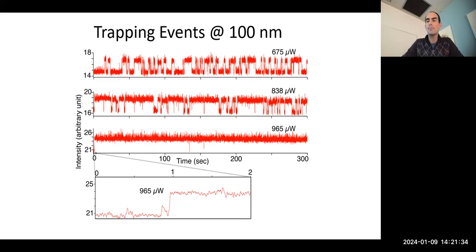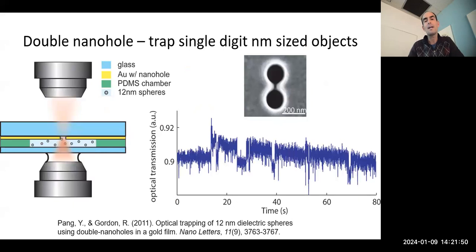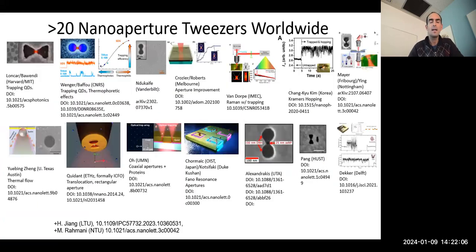With a very small amount of power, less than a milliwatt, which is small for an optical tweezer, especially when trapping 100 nanometer particles—really tiny particles for optical tweezers—we could hold onto it indefinitely. But then we pushed it even further using these shaped double nanohole apertures, which provide sharpness to the metal to localize the electromagnetic field and make the trapping force even stronger.